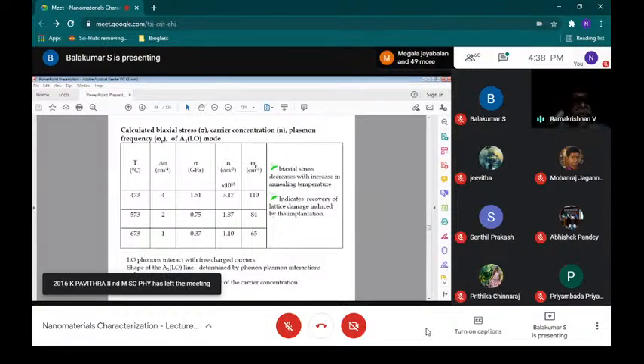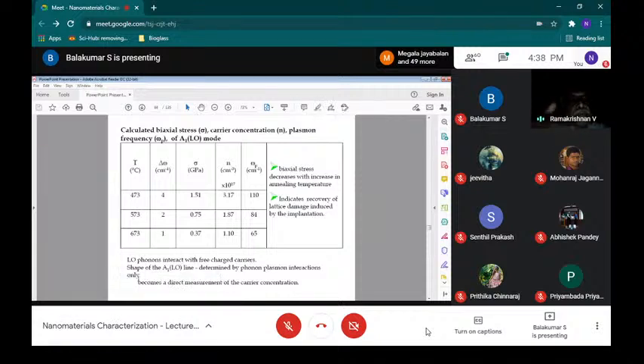So delta omega is at 4 to 1. Delta omega reduces because we are moving more toward crystallinity, because more damage happened. But the annealing is less at lower temperature, so the rearrangement of the crystallites will be less, but the shift will be high. So you can see delta omega is 4 to 1. Then you can see the biaxial stress decreases with the increase in annealing temperature.